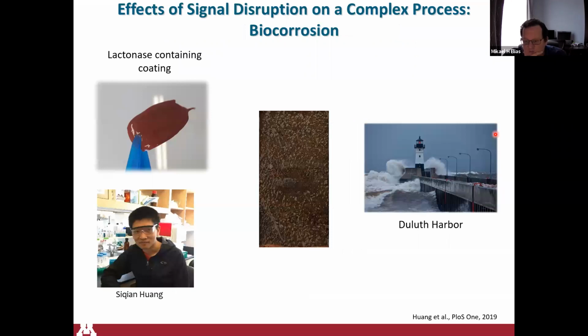And this is some work that has been performed by Dr. Huang here. He initiated this work in the Duluth Superior Harbor. He first managed to coat our enzymes and formulate them into a variety of coats. This is an example here in this top coat from Hempel. And we initially tested these coatings on steel in the Duluth Superior Harbor for corrosion. There is a very significant microbially induced corrosion in the Duluth Superior Harbor that has been accelerating in the last 20 years. And so we thought that this was a great experimental site to test that.